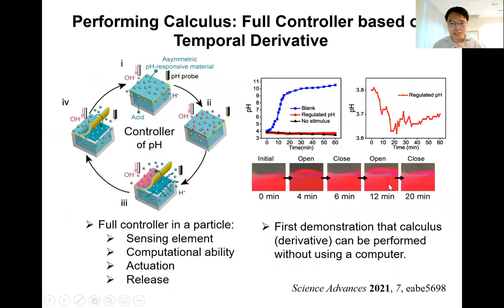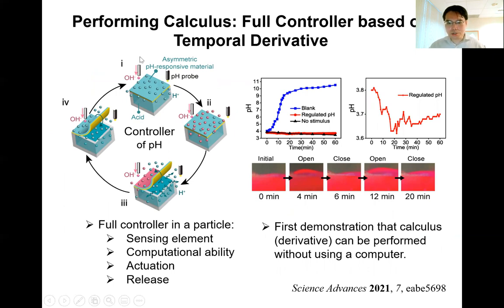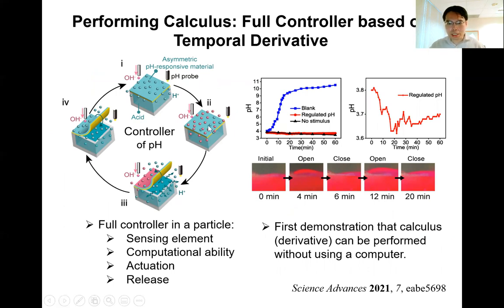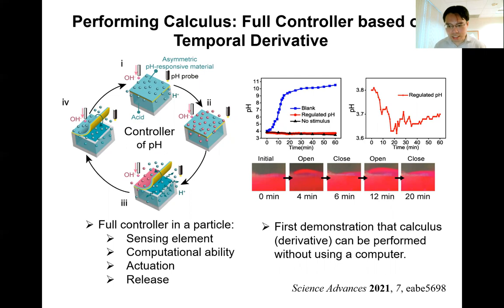If we include not just any chemical within the reservoir but an acidic solution, we will be able to build a full controller of pH based on analyzing the temporal derivative. If we use a disturbance of a basic solution, it will allow the hydrogel to open and release acid into the surrounding environment to control the pH. From experiments, we are able to control the pH at the desired value. We have fabricated a full controller that includes the sensing element, computational ability, actuation, and release. From the literature, calculus — specifically the derivative — has always been performed using a computer. So this is the first demonstration that calculus can be performed without the use of a computer.